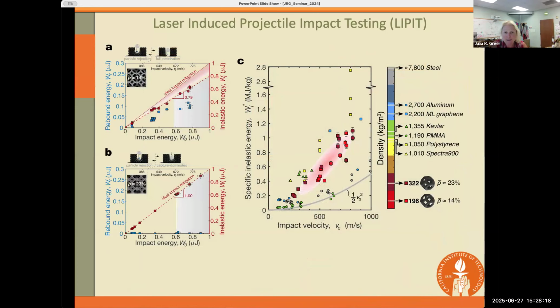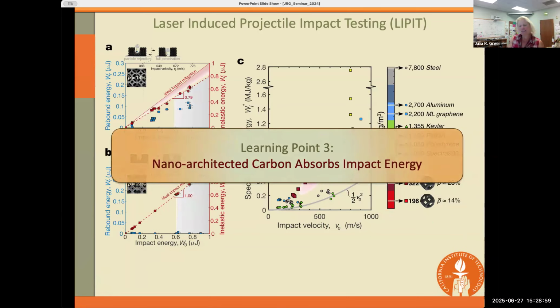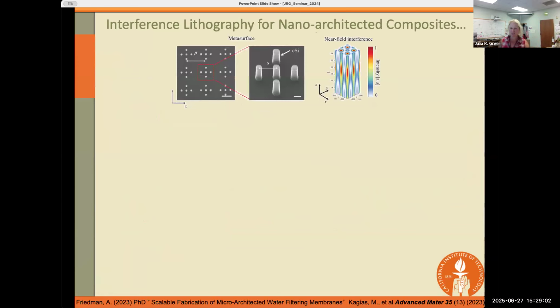And in fact, if we were to plot the specific inelastic energy as a function of impact velocity, you can see that we're comparable, that this nano-architected carbon performs similar to Kevlar, if not outperforming some of the traditionally used composites for energy absorption. And the plots on the left are showing this impact mitigation for the rebound energy versus impact energy. So you can see the plot on the top is 14% relative density, and you can see that it gets close to ideal impact mitigation versus 23% relative density. And that one, you can see how much the relative density of the nano-architected material really contributes to its impact mitigation. So we were pretty excited about this because it turns out nano-architected carbon absorbs quite a bit of energy.